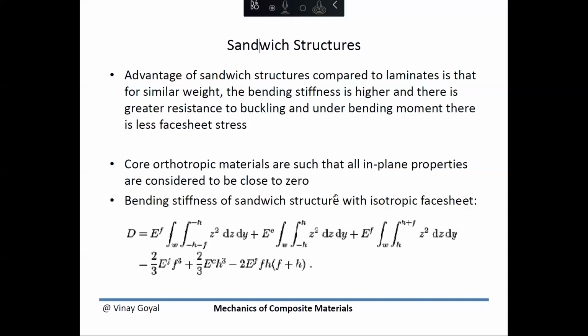If I were to calculate the D matrix for isotropic face sheets with some sort of core thickness, we have that the bending stiffness can be found to be the face sheet modulus, which is fairly high compared to the core modulus in the middle term. But I'll go ahead and integrate that. I'll integrate the bottom face sheet through the thickness, from minus h minus f to minus h. And then I have the core, which goes from minus h to h. And then I have the face sheet, which goes from h to h plus f.